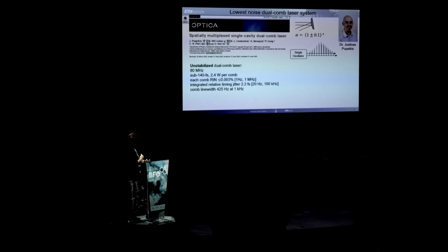So this is now based on these diode-pumped solid-state lasers. So it's ytterbium-doped solid-state lasers. And when we did it with this spatial multiplexing, where this biprism has only 1 degree, but it changes a little bit the path length inside the laser cavity, we built an 80 megahertz laser cavity, sub 140 femtosecond. In each comb, we had 2.4 watt of average power, so plenty of power. And the RIN, the relative intensity noise, in each comb is extremely low, and the relative timing jitter is 2.2 femtosecond.